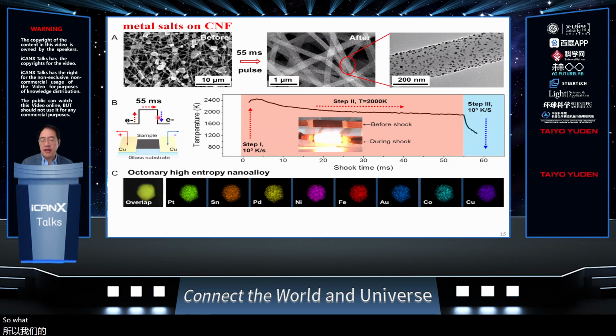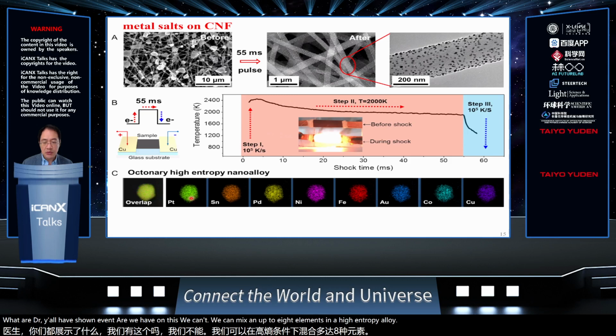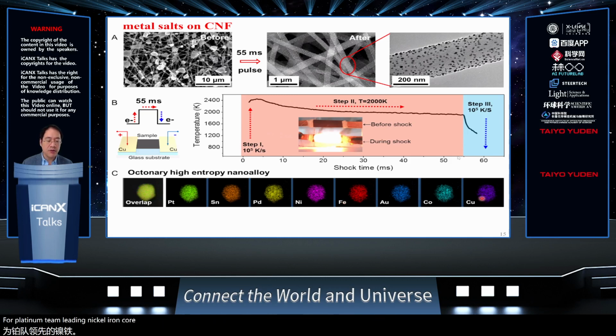So what happened is that we initially put on this carbon substrate some chloride or nitrate salts. We put multiple kinds of salts like platinum chloride or palladium chloride salts, and these salts are microns in size. But what we found after this thermal shock treatment is that it has decomposed into these nanoparticles. And in fact, what Dr. Yao has shown is that with this, we can mix up to 8 elements in a high entropy alloy: platinum, tin, palladium, nickel, iron, gold, cobalt, copper.